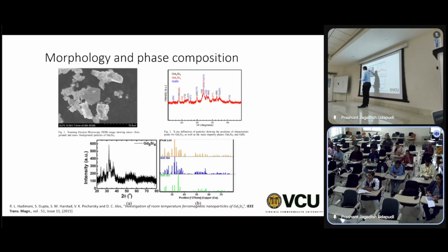5 atoms of, I'm just making it up, it doesn't say 5 atoms, it gives in terms of percentage. Okay, it will say, so this is 60% gadolinium and 40% silicon. That means, or 55 and 45%, 55% gadolinium and 45% silicon. That means I know it's gadolinium silicide.